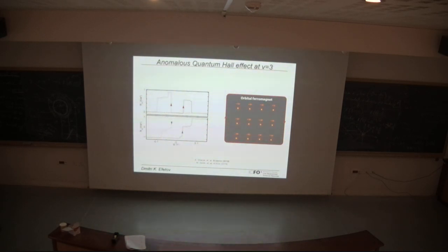So capacitance, there was one paper by Ray Ashoori's group. They're just next door to Pablo, so I think Pablo gave them the samples, but they can measure capacitance. As I said, I don't think anybody right now expects any symmetry in this system. So there's for sure asymmetry, but also from just transport you see asymmetry between everything. But capacitance, there's again this group here at Santa Barbara, they're good in capacitance. Then in Pablo's case, they're doing capacitance. But I don't think anybody really looked at the superconductivity or correlations in this regime yet. It's a little hard to do the experiment.